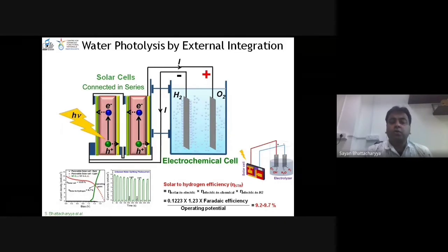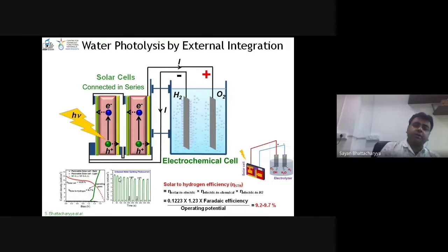how good this solar cell is. Okay, if you use a solar cell which has very good efficiency, you of course get more. And we have got something like close to 10%, because the solar cells and this electrolyzer we made in the lab. You see that over time the current slightly drops, it is on and off, dark and light, and it slightly drops, but it's still okay after some cycles.